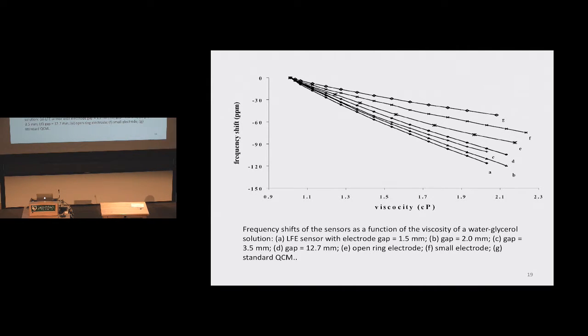Now the question is, why did this thing also respond better than the QCM? Well, the QCM has got this gold layer on the top. And that gold layer helps to shield the measurements of the viscoelastic properties. So the actual material, in this case a water glycerol solution, the actual acoustic energy has to penetrate through the gold to get to it. On the LFE, it doesn't need to do that. The LFE surface is bare. So the actual penetration is directly into the water glycerol solution.